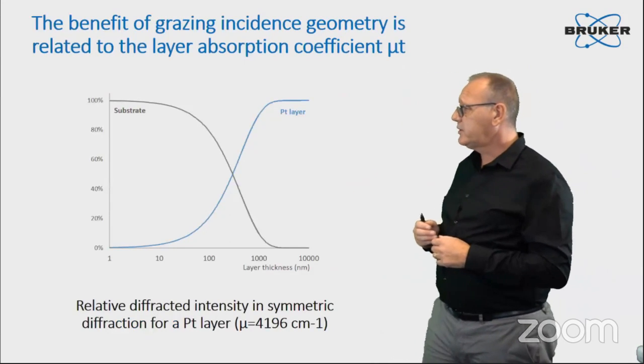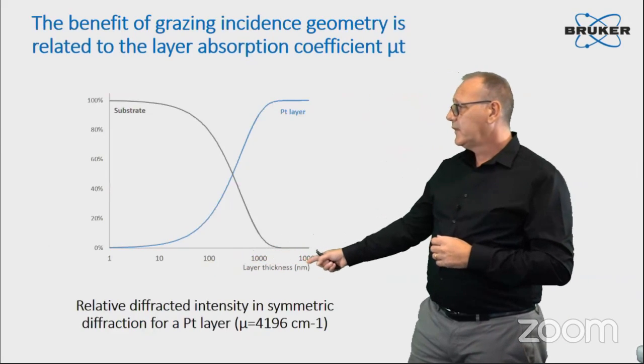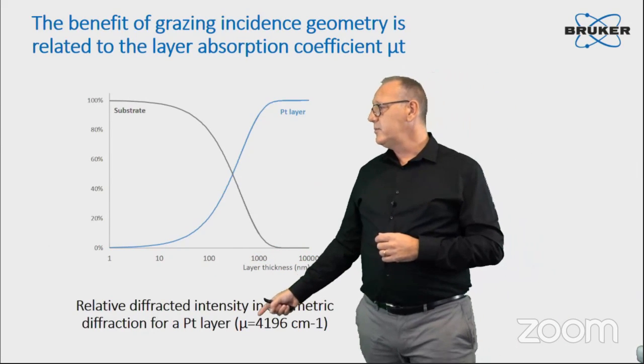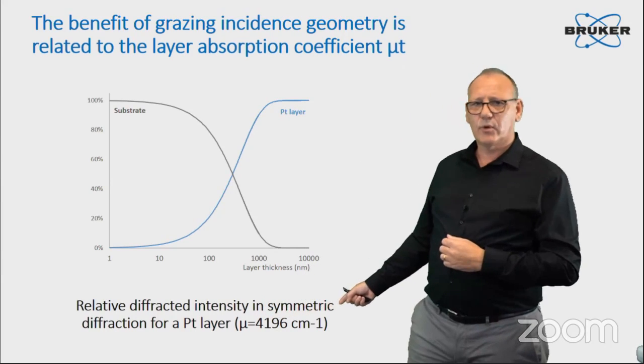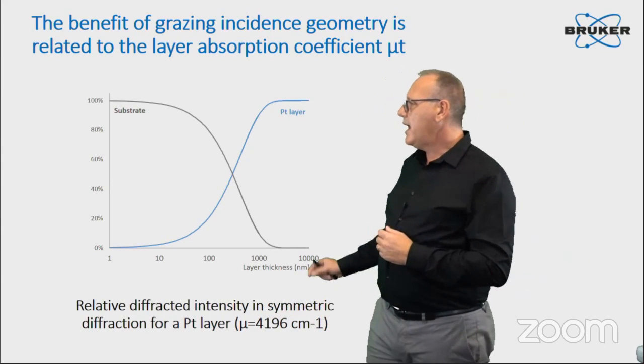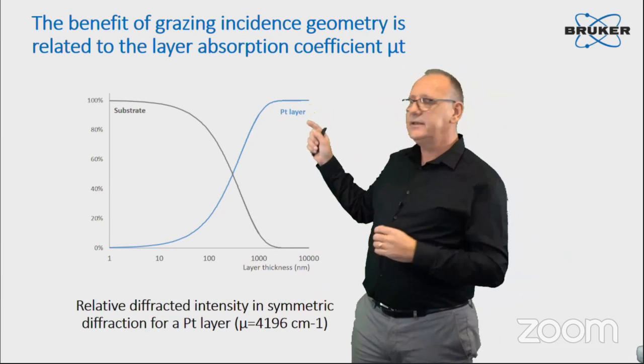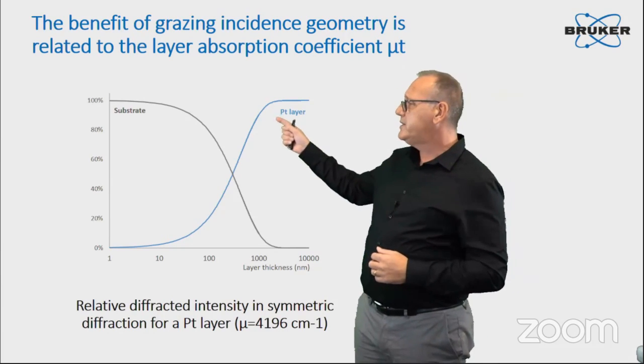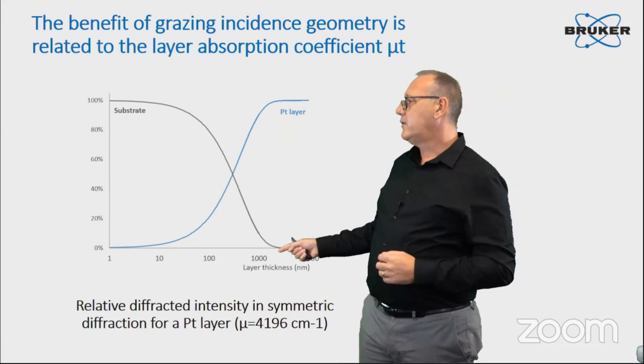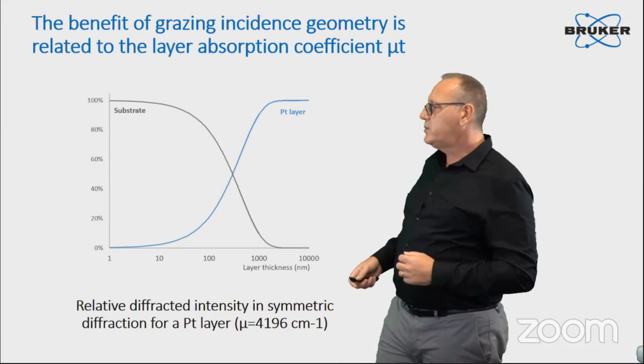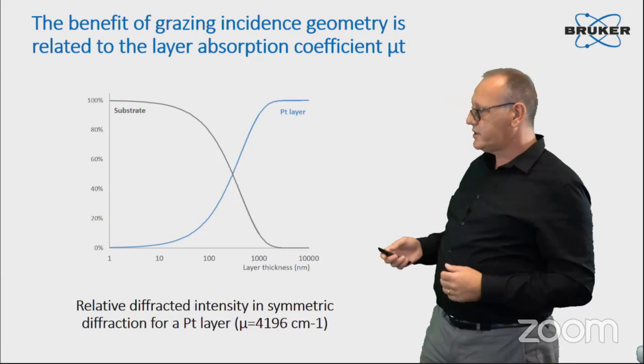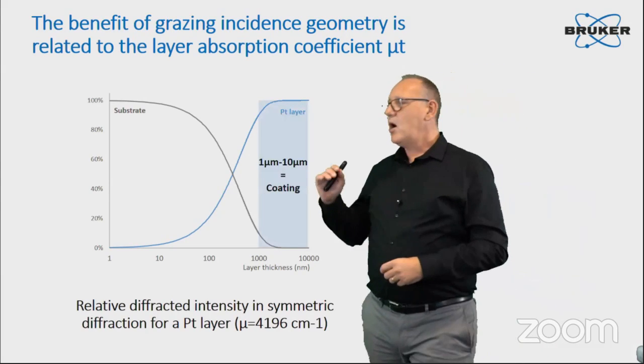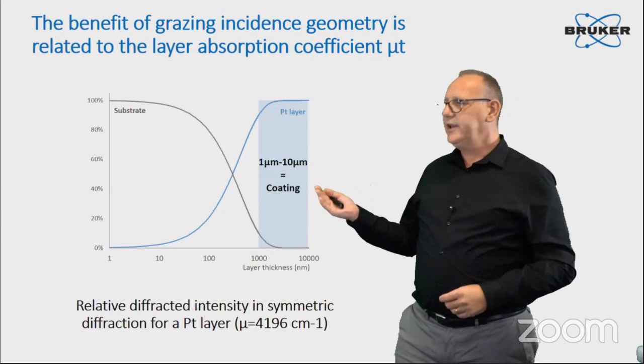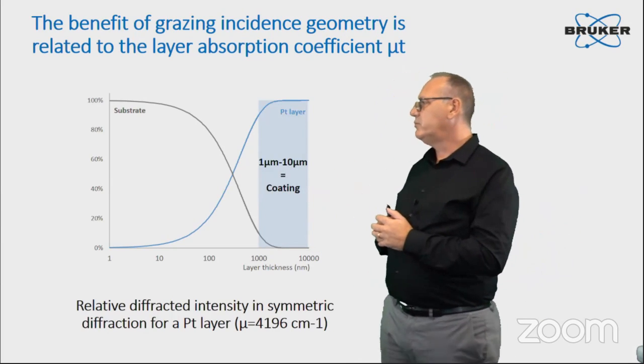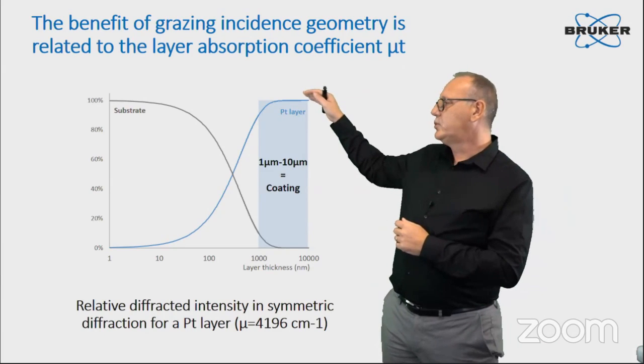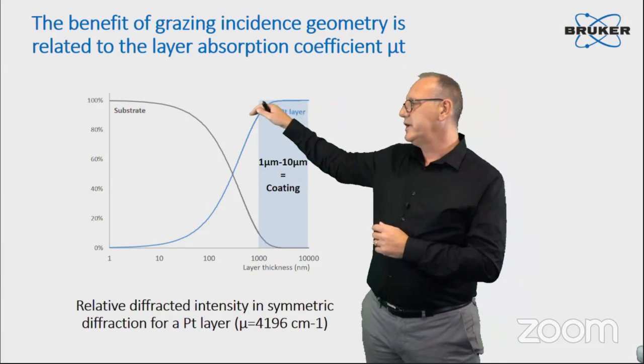We have here on this plot the thickness of the layer. We have made the calculation for a platinum layer, which has a pretty high absorption coefficient. And we display here the relative intensity in symmetric diffraction of the platinum layer versus the substrate signal. What we see, we can actually define different ranges. What we see is that above 1 micron, there's no need to set up any GID measurement because you hardly penetrate into the substrate, you just start penetrating somewhere here.